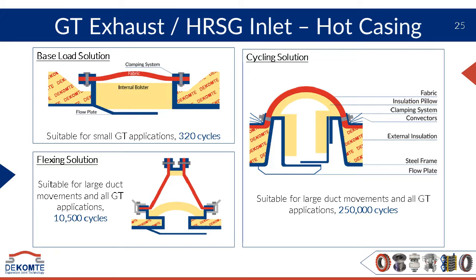And the internal insulation is split so that during a cold state it's separated, during a hot state it's coming in contact with each other. This system adds some complexity because in order to solve the primary and secondary failure modes, we now need a much more durable fabric solution, and we also need a convector system to manage the heat path through the studs and maintain, as we showed on the previous slides, less than 200 degrees for the durability of the PTFE